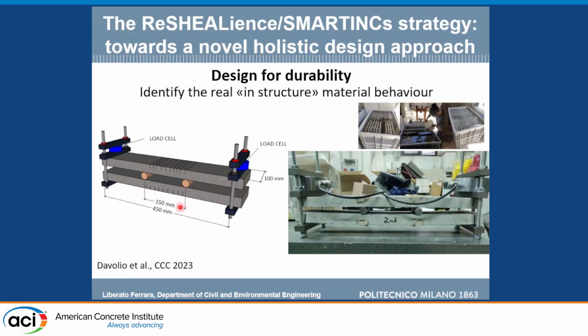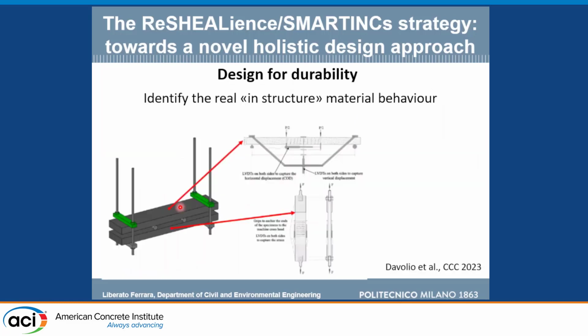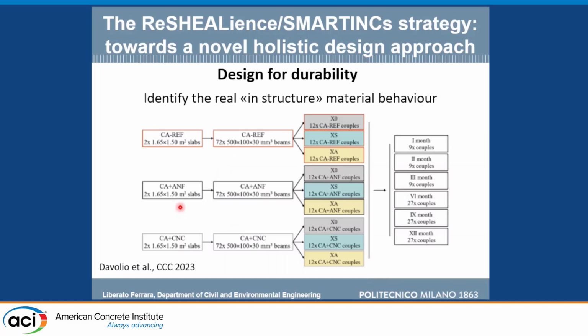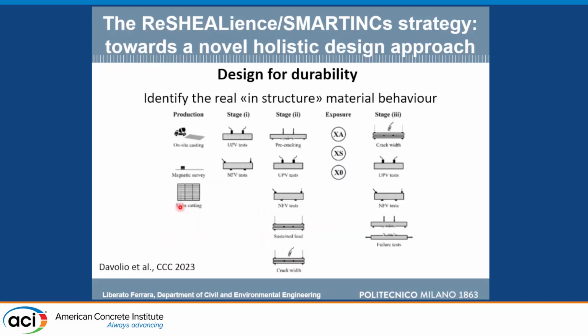Then we wanted to see, but this assumption of removing the attacked layer is too severe. The material probably is going to keep its performance. So we developed this setup to keep the material and the specimen under sustained loading while they were exposed to chlorides or to geothermal water or to tap water for comparison. And at the end of 1, 2, 3, 6 months and so on, we removed some of the specimens and tested them in bending or in direct tension. So it was a very huge experimental campaign, more than 2,000 specimens which were tested up to 1 year exposure, containing either alumina nanofibers or nanocellulose, and were investigated.